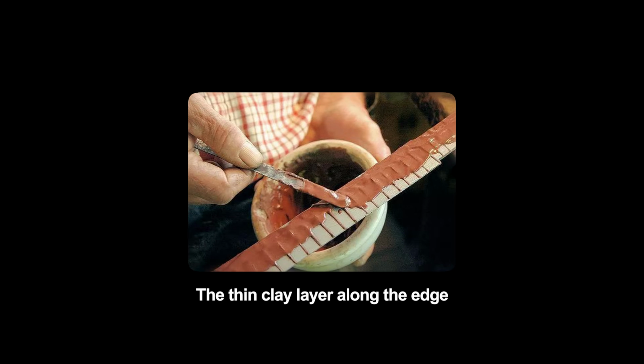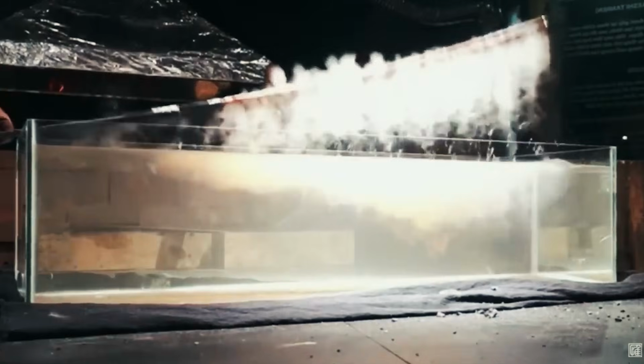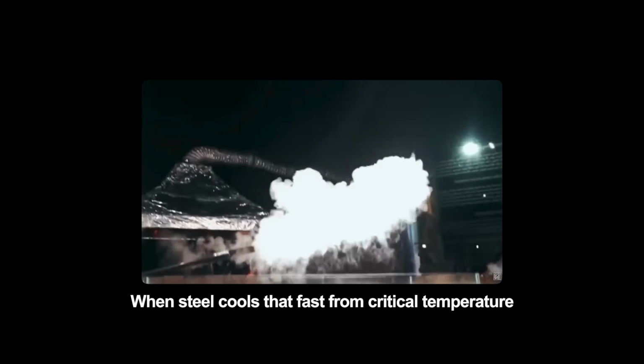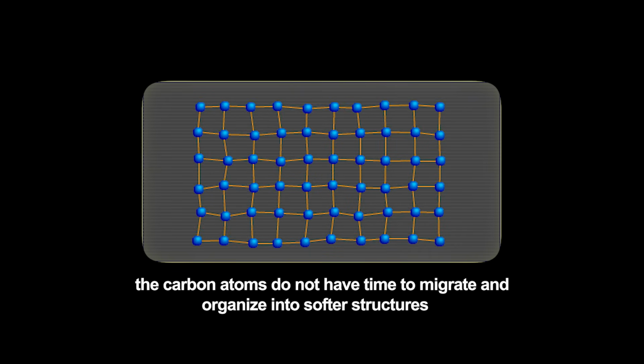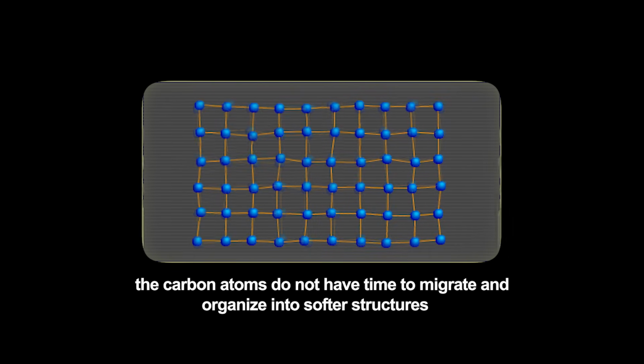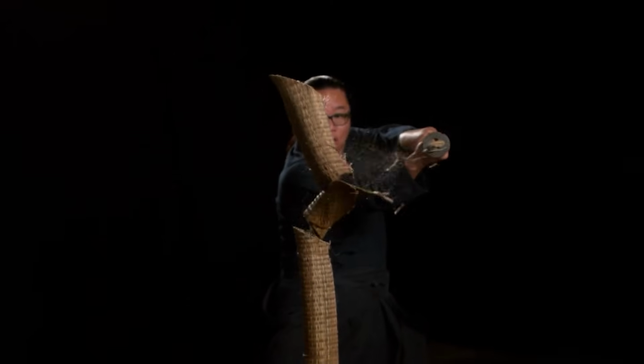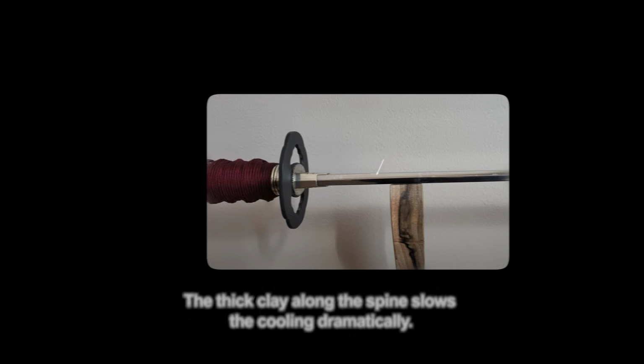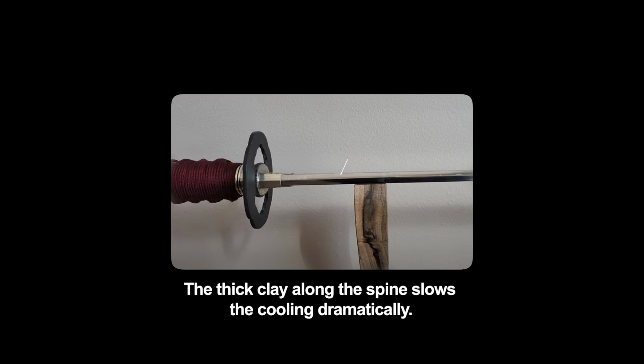The thin clay layer along the edge allows that section of the blade to cool almost instantaneously. When steel cools that fast from critical temperature, the carbon atoms do not have time to migrate and organize into softer structures. Instead, they lock into a crystalline lattice called martensite, extremely hard, capable of holding a razor edge through repeated cutting. The thick clay along the spine slows the cooling dramatically.